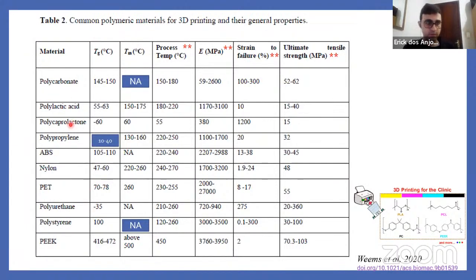Let's take a simple example here. ABS is an amorphous polymer, so it doesn't have a melting point, just a glass transition, and its glass transition is around 80 Celsius degrees. This is why ABS can be applied just up to 85 Celsius degrees at maximum, because it will start to soften at higher temperatures. On the other hand, we have an advanced plastic, PEEK, which can be applied up to 350 degrees because its glass transition is around 400, and its melt transition is around 500, for example. So it's a polymer that resists really high temperatures.